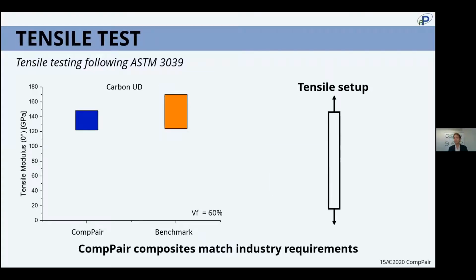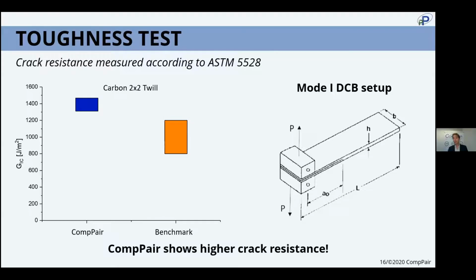We've done exactly the same for tensile setup. Here you see the tensile modulus for CompPair composites in comparison to industry benchmarks. And then at the end, what we have said at the beginning is the fact that we have a better crack resistance, so better toughness of those composites. And you see here typical toughness value G1C for, again, CompPair composites higher than the industrial benchmarks that we could find.